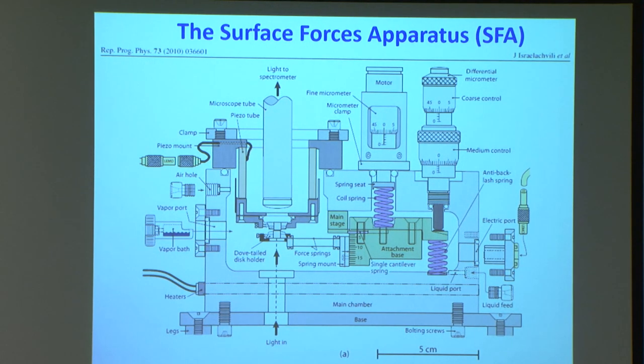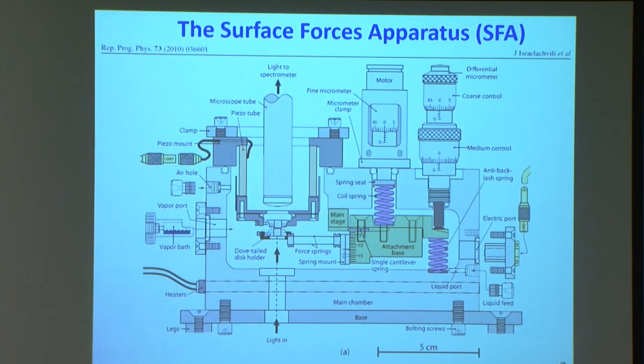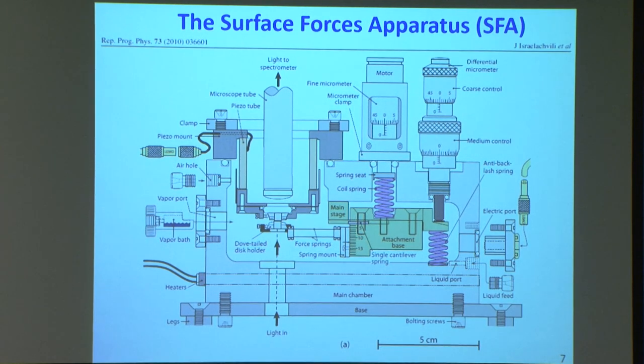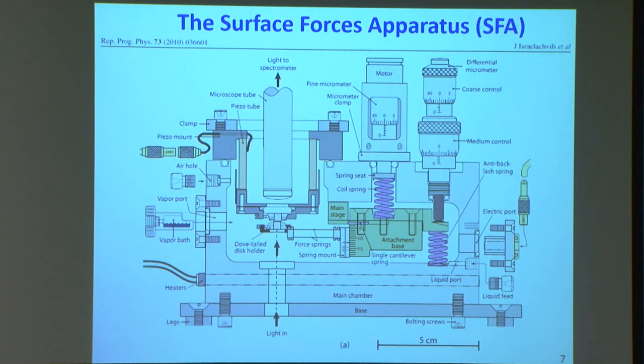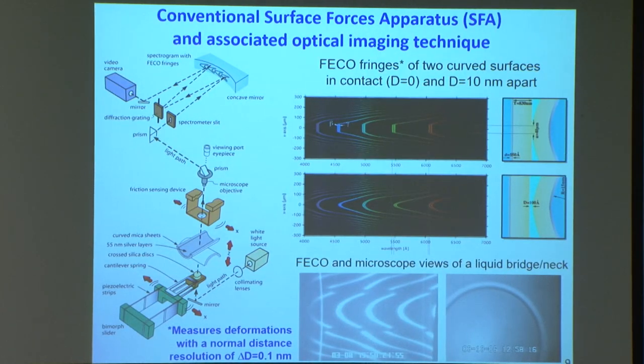Some of the results I'm going to show, many of them are to do with the surface forces apparatus, and I won't go and describe it, but I'll just mention that the two surfaces facing each other, it's a bit similar in some ways to an AFM, except that it uses extended surfaces, and there are various methods of changing the distance and controlling it using springs and piezoelectric crystals. One can change distances to within an angstrom, and using an optical technique that allows one to look at the surfaces and measure their deformations in real time. And this has been used for many years now to look at forces between macroscopic surfaces in liquids or vapors, adhesion, as well as sliding laterally.